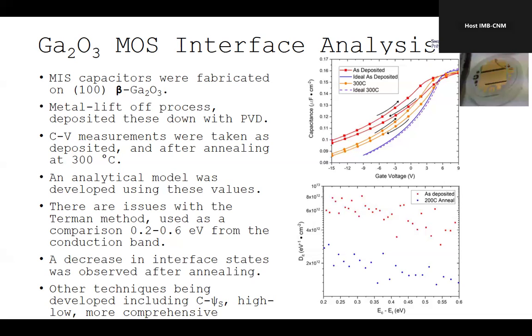Yeah, very good questions, Amador. On the face of it, gallium oxide has a much higher critical field than even silicon carbide. That means that for trench devices, the field in the oxide is going to be much higher again than even in silicon carbide. So for sure, there are going to be issues in terms of reliability.